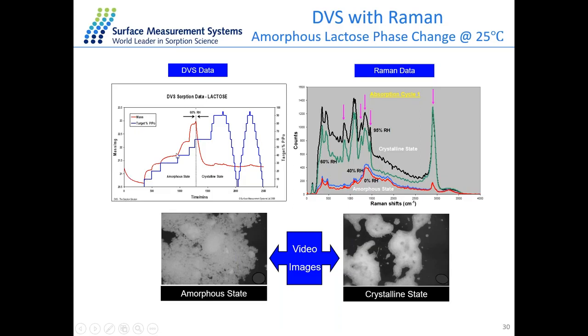And our red line is actually the change of our sample mass in reference to the changes of relative humidity. So what we can see here first is we're first drying the sample at 0% RH and then increasing the relative humidity in the system. And this leads to an uptake of the probe molecule here. What we can see at this place, around 60% relative humidity, is that we're actually getting a change in our sample. And this is going from an amorphous state to a crystalline state.